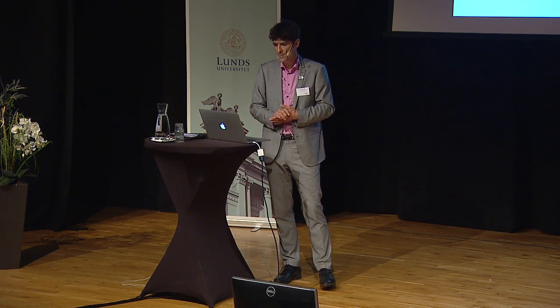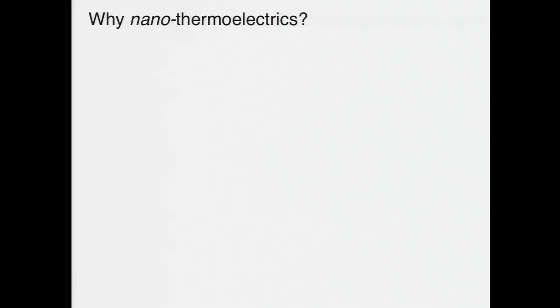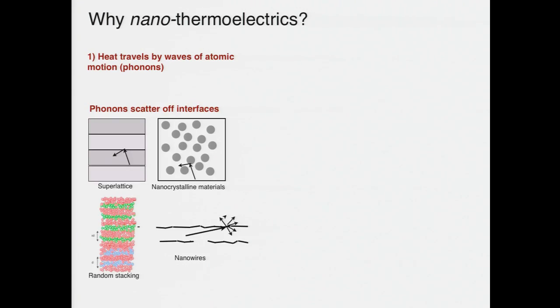This then explains why people are interested in nano thermoelectrics. The fundamental insight for this was provided in particular by Mildred Dresselhaus more than 20 years ago, who wrote a couple of what she calls very simple papers, but they contain a lot of truth. The first insight is that if you provide nanostructuring to materials, you generally suppress heat flow.